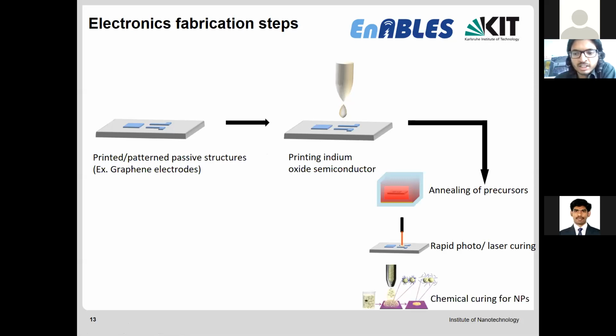And then we can also use something called chemical curing for nanoparticles. In this case, instead of a precursor, we use nanoparticles, which is the same material, but the precursor is a pre-stage to the indium oxide, and the nanoparticle is just the indium oxide nanoparticles. These are two varieties of the same thing. We can use chemical curing in order to get very stable and dense films.